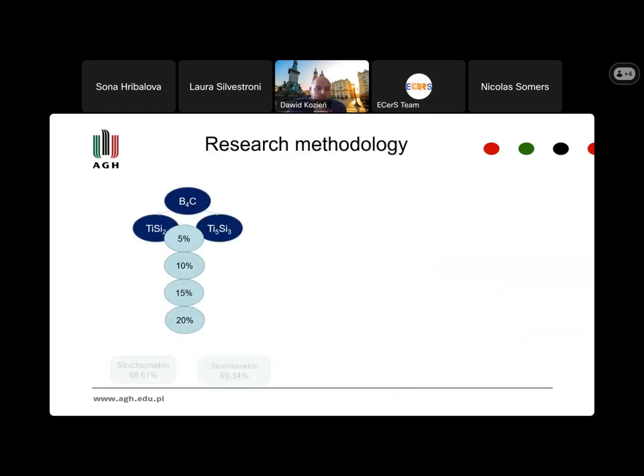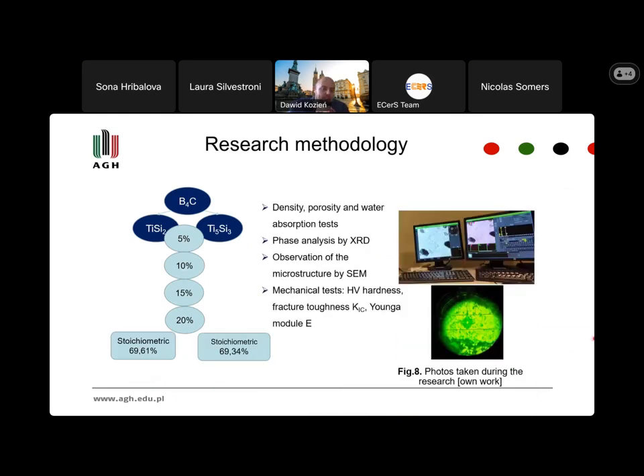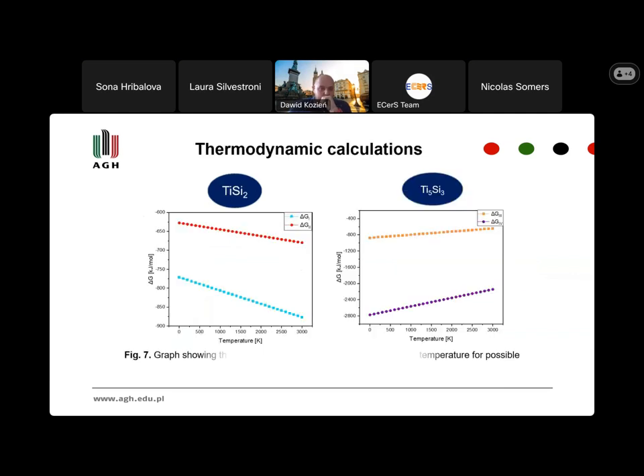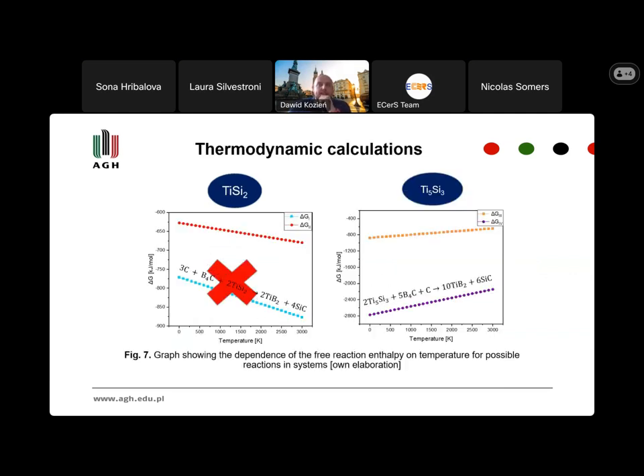After that, we prepare the samples and compare the results with additives of this intermetallic of 5, 10, 15, and 20%. What is most important in our research is that we start with a stoichiometric sample. Stoichiometric means that we assume that 100% of our raw material during the sintering will be changed into other phases. So in this method, we think that it should look like this.